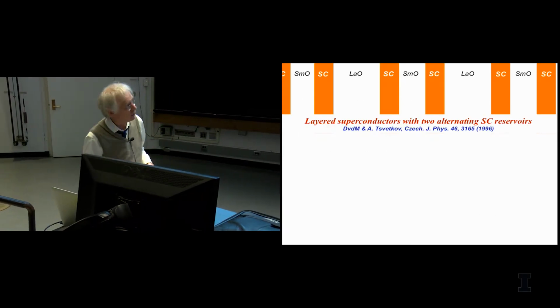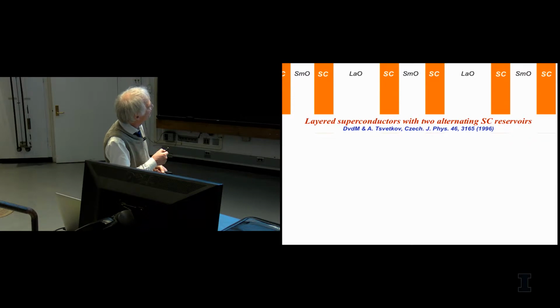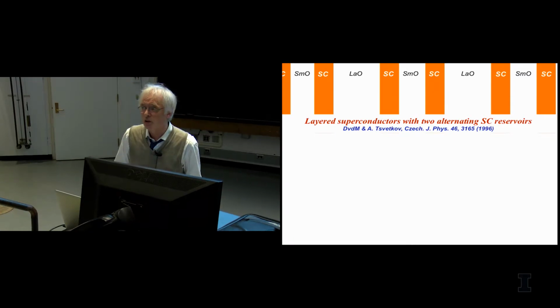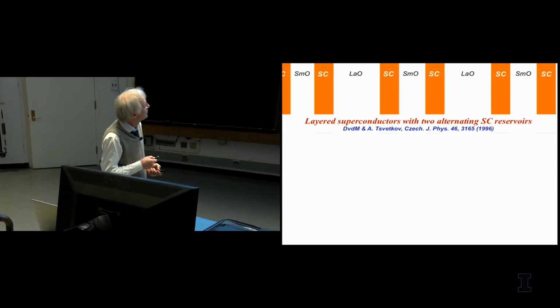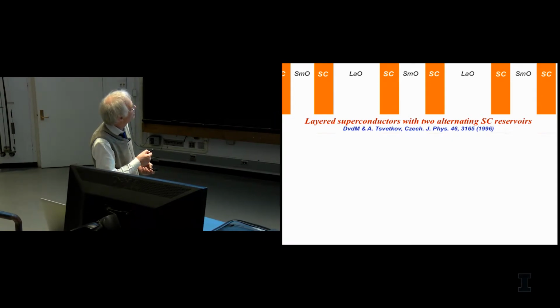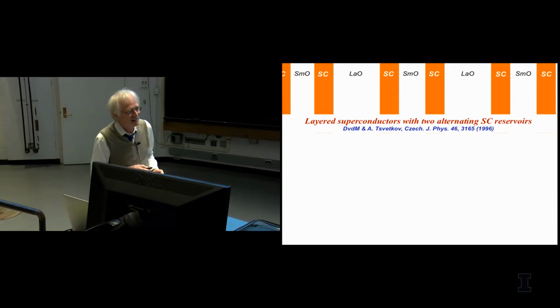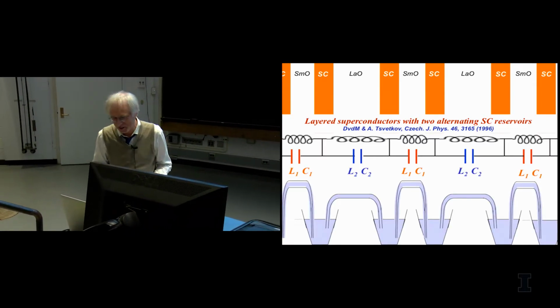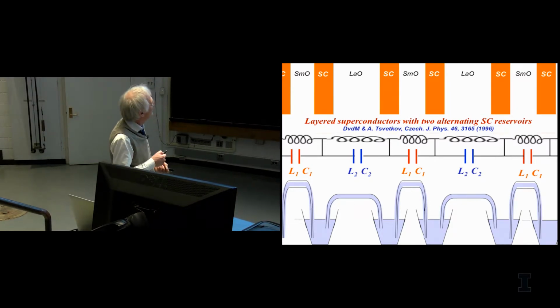There are two, actually, but I'll talk about one of those. So if you now make these same kind of superconducting stacks as before, but you make an alternation of one kind of junction with samarium oxide and another kind of junction with lanthanum oxide, you alternate in this way, then actually, even though the superconducting layers themselves are still equivalent, they just have lanthanum oxide left and samarium oxide right, or vice versa, otherwise it's equivalent. But still you have now a larger unit cell which contains indeed two reservoirs of superconducting fluid. At the time we were thinking about this in 1996, this is one of the most cited papers in the Czech Journal of Physics. You know, 100 or 150 citations. It was a failed PRL, I should say, that we put in as a conference proceeding.